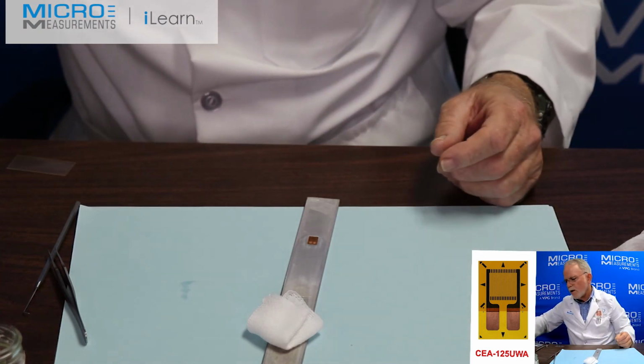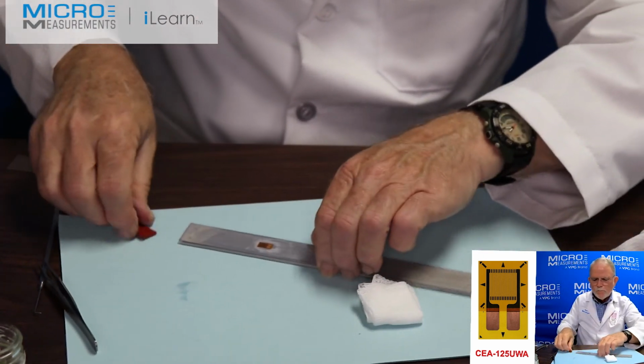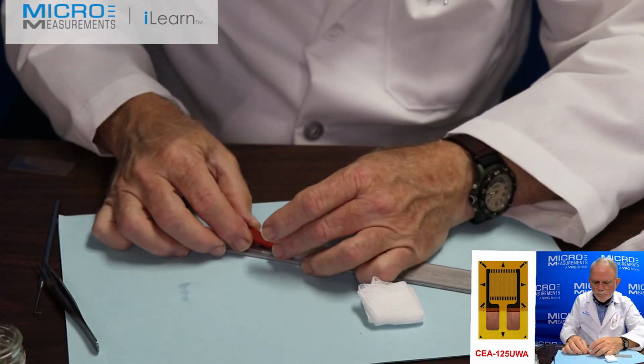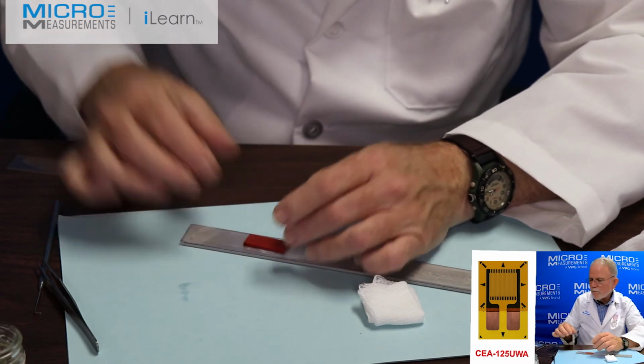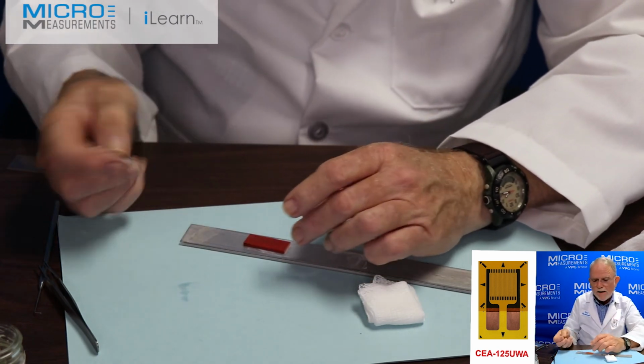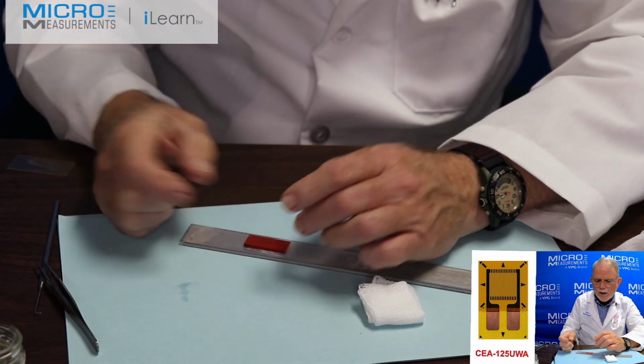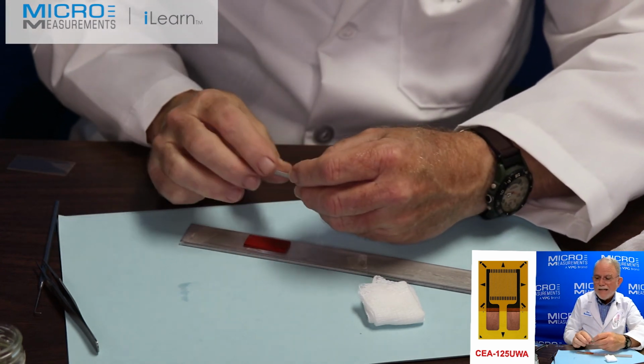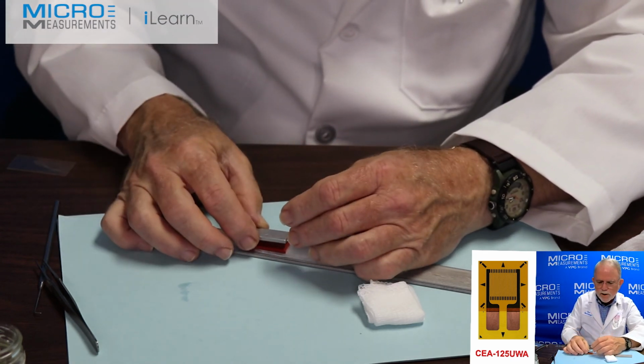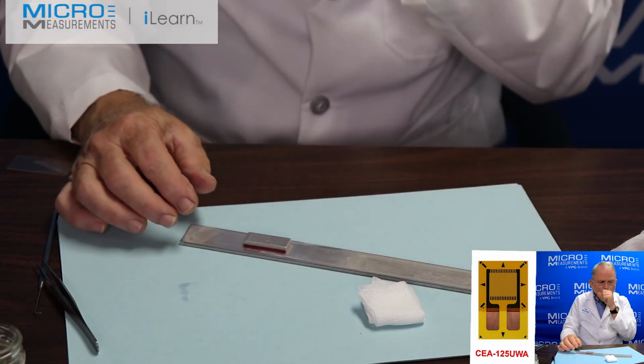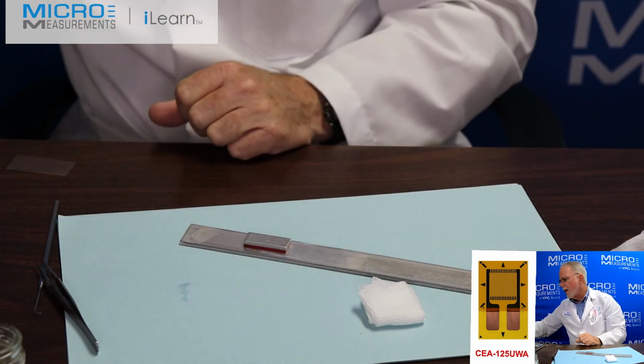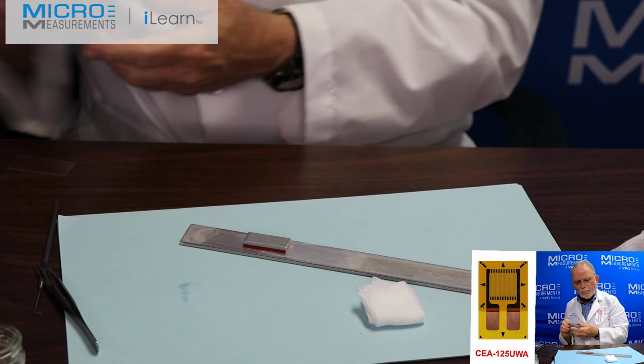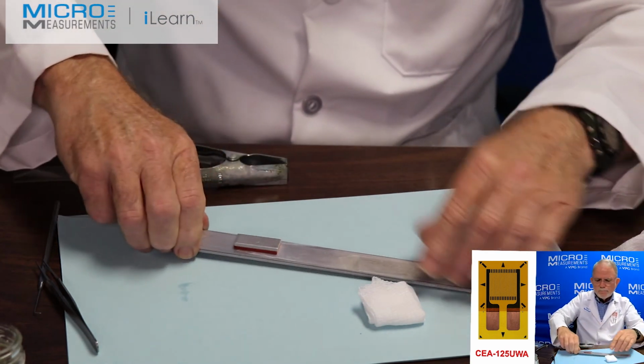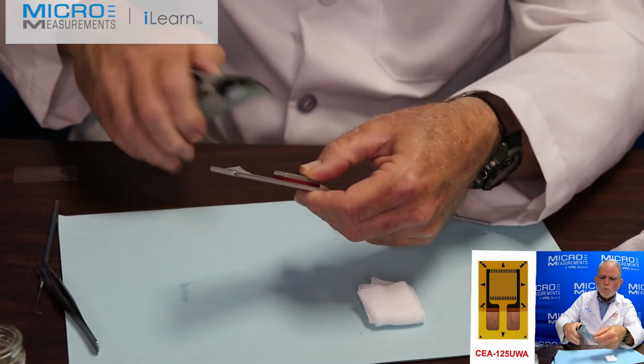and then I'm going to take the silicone gum pad for the clamping pressure. And this particular adhesive system requires somewhere between 5 and 20 psi of clamping pressure. Note I said psi, or pounds per square inch. There'll be an aluminum backing plate which will distribute the clamping load. And then I will clamp it up,